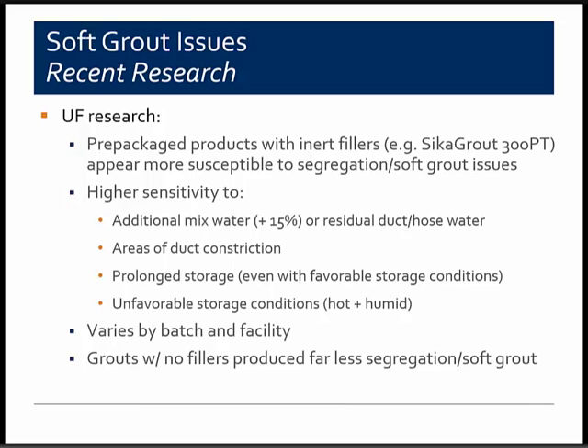And in addition, the University of Florida has performed some research to attempt to understand the how and why of the soft grout formation. And what they found is that the prepackaged grout materials that contain inert fillers like SikaGrout 300PT and some others are susceptible to segregation and soft grout problems under certain conditions, much more susceptible than Portland cement grouts or other prepackaged grouts that don't contain inert fillers. And the pre-bagged grouts with fillers appear to have a much higher sensitivity to water content and product storage conditions, as well as certain tendon geometry considerations.